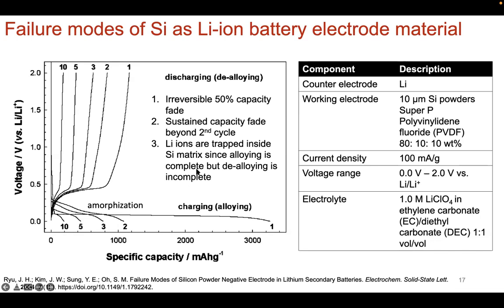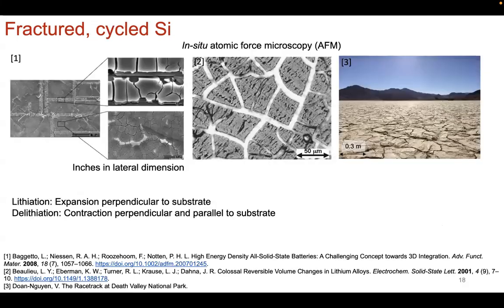And what happens here in these micron-sized particles is that once lithium comes in during lithiation, they sort of get trapped there and they don't come back. So that's what you see, that your second lithiation cycle, you start off with what you left off with for a delithiation in the first cycle, and then you basically just start to gradually lose active material. Okay, so there are trapped lithium ions within the silicon matrix, and you form whatever phase that you form, and they're not being released back during the delithiation phase. So then the strategy for designing is, okay, let's move to smaller particle size.